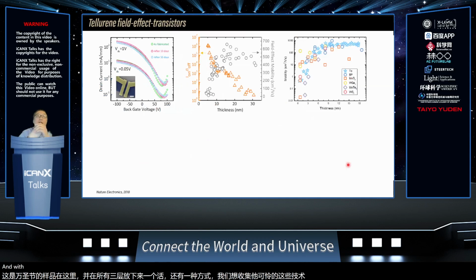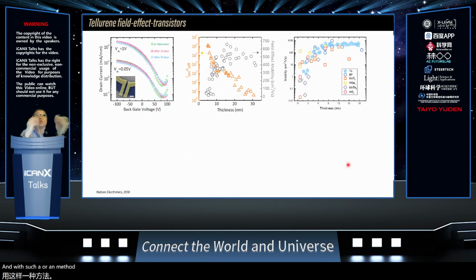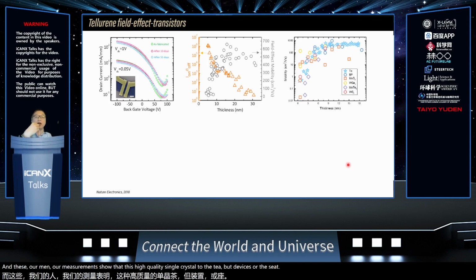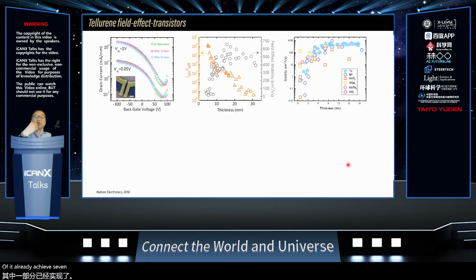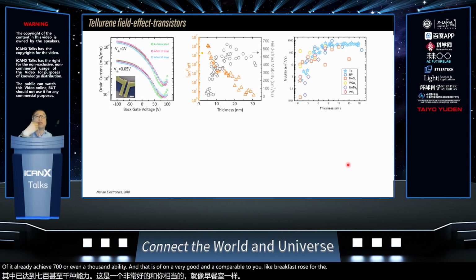With such a method to produce a large quantity of high quality two-dimensional Te crystals, we were able to probe the fundamental electrical properties of these materials. Our measurements show that these high quality single crystal 2D Te devices exhibit very high Hall mobility at room temperature without any advanced device engineering. It already achieved 700 or even 1,000 mobility, which is very good and comparable to black phosphorus, but much more stable than black phosphorus.